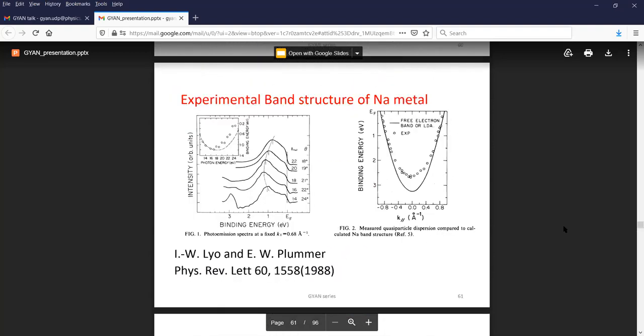The information you can get — particularly for quasi-1D and 2D systems — is the band dispersion of electrons in the solid. The points where they cross the Fermi level constitute the Fermi surface crossings, so you can determine the Fermi surface of a solid. For example, for sodium metal, if you do the valence band as a function of angle or photon energy, you will see a band changing its energy, and plotting versus angle maps onto the crystal momentum. For a simple metal like sodium, it's nearly a free electron metal, and the experimental dots match with the calculated free electron band dispersion — a parabola.